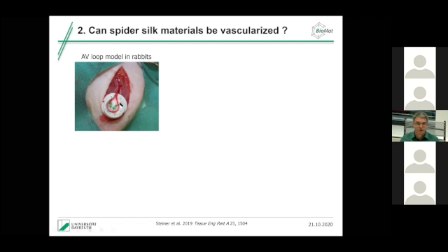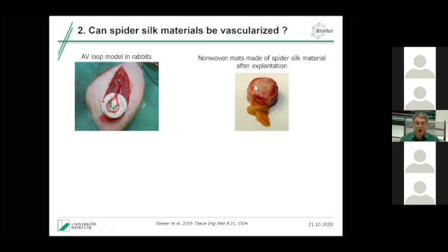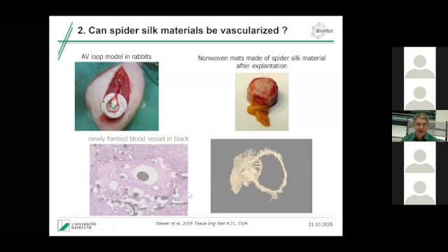So you see here, actually the artery is coming in, and then it's going over into a vein, and it's in a Teflon chamber. And inside the Teflon chamber, now you can place a lot of materials. And if they are actually good materials, the vascularization from this AV loop into the material will start. And here we tested our spider silk. It's typically in the rabbits for 2 weeks and for 4 weeks. And then it's checked if after 2 weeks or 4 weeks, any new blood vessels have grown. So this is how the explant looks after 4 weeks. And this is what happened.